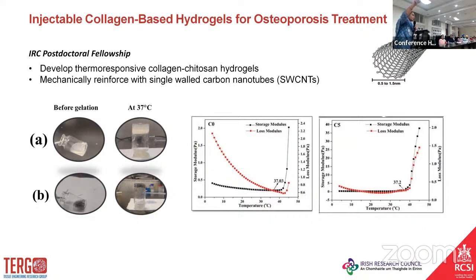You can see in the figures on the left side, before gelation it was a liquid, but when it moved to 37 degrees, it became a gel. These graphs are from the rheometer, a technique to investigate the gelation temperature of a material. The storage modulus is the mechanical property of a gel, and the loss modulus is also a mechanical property, like Young's modulus for those who study physics. Around 37 degrees, the loss modulus decreases but the storage modulus increases. It means the solution is turning into a gel around 37 degrees.